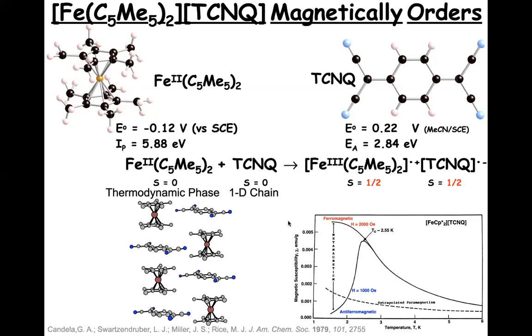And this is, as I illustrated a few slides ago, typical of a metamagnet, where it's an antiferromagnetic ground state with a ferromagnetic excited state that you can reach, in this particular case, above a critical field of 1300 Oersteds applied field. So below 1300 Oersteds, it's an antiferromagnetic material. Above 1300 Oersteds, it's a ferromagnetic-like material. So this suggested to us that perhaps we can stabilize a ferromagnetic ground state instead of an antiferromagnetic ground state.